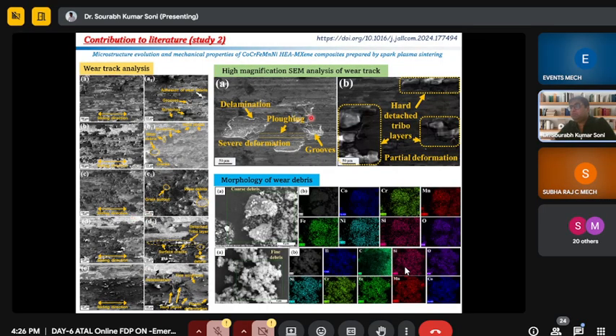So you can use these techniques also. So here we observe the deformation, ploughing, grooves within the specimen. So we can analyze this and say in our publication, so that reviewer will correlate this. And then we must observe the morphology of wear debris. Here we can see the fine debris, and here we can see the coarse debris. So we can relate what is the implication of these both in our specimen.